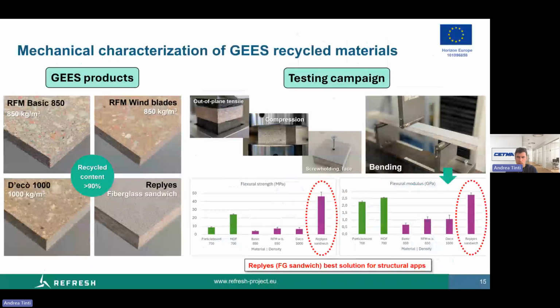First of all, as reported during the previous presentation by Giorgio, the mechanical recycling process developed by GEES Recycling leads to semi-finished flat panels with varying composition, density, and then mechanical properties, possibly to be reinforced with fiberglass skins in a sandwich structure. So several types of GEES mechanically recycled panels were selected as candidates for the intended application, and they were mechanically tested. Based on results of material testing, the sandwich panel was found to be the best solution for new structural applications loaded in bending, like the one we are working on.